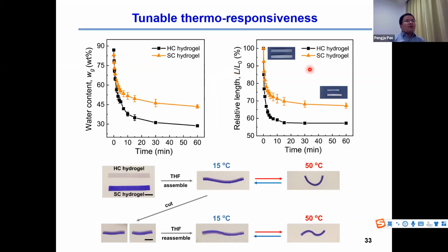However, because the stereocomplex hydrogel has a strong physical network, its water desorption and shrinking are less obvious than the homocrystalline gel. Using the different shrinking ability of stereocomplex and homocrystalline gel, we prepare a bilayer actuator. One layer is a stereocomplex gel. The other layer is a homocrystalline gel. The bilayer can change shape reversibly in cold water and hot water.